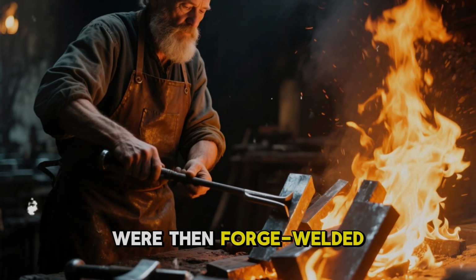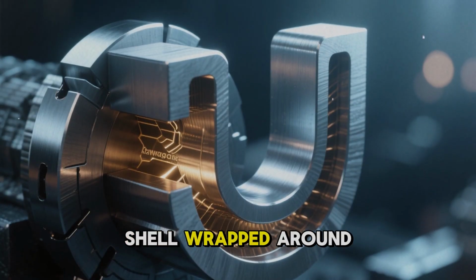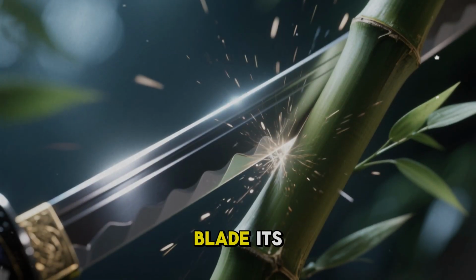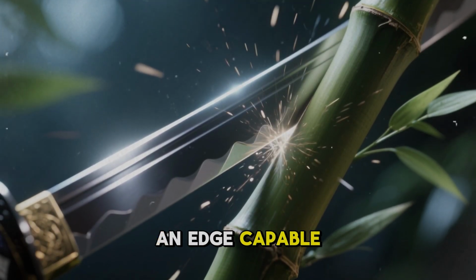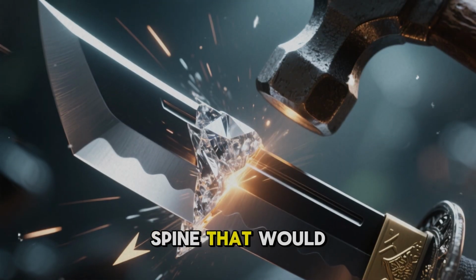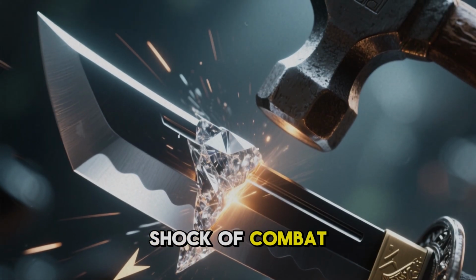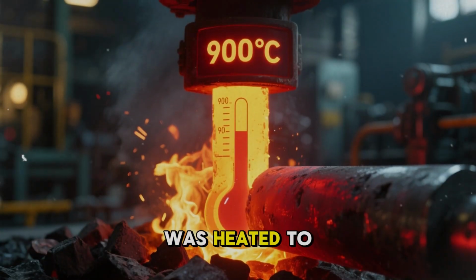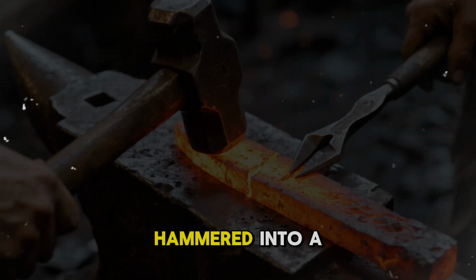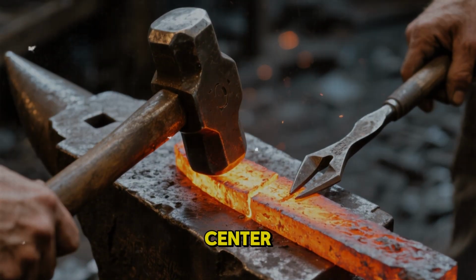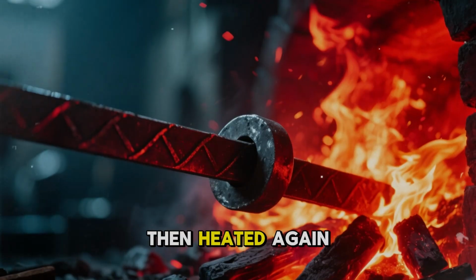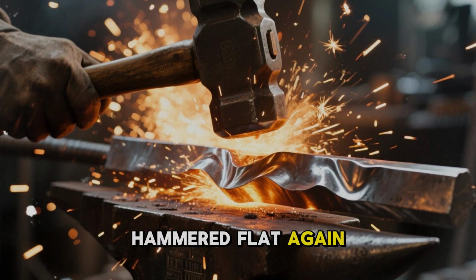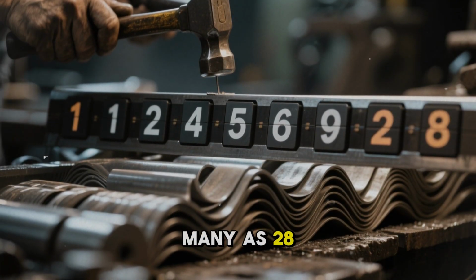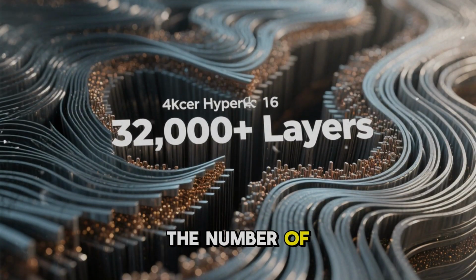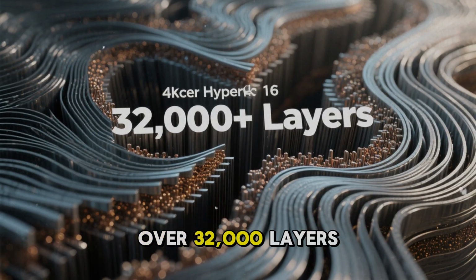These different steels were then forge welded together, the hard outer shell wrapped around the tough inner core, giving the finished blade its legendary dual nature, an edge capable of cutting through bone, mounted on a spine that would bend rather than snap under the shock of combat. Then came folding. The assembled billet was heated to around 900 degrees Celsius, hammered into a flat bar, scored down the center, and folded back on itself, then heated again, hammered flat again, folded again. This process was repeated anywhere from 12 to as many as 28 times. Each fold doubled the number of layers. 15 folds produced over 32,000 layers of steel.